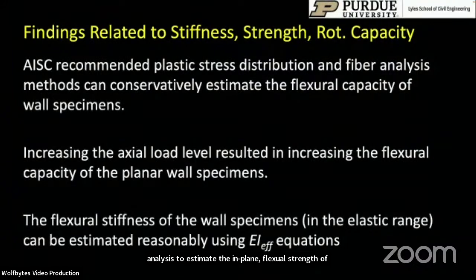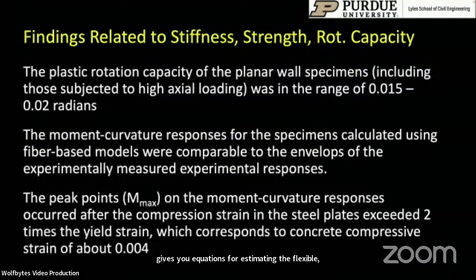It tells you that if you have axial load, you need to account for that, and it gives you equations for estimating the flexural stiffness of the wall specimens that is based on this research as well. In the commentary, it points out that the plastic rotation capacity of the planar wall specimens was in the range of about 1.5 to 2% in radians, and the moment curvature responses compare very well with the fiber-based models, and tells you some more recommendations on how to calculate the in-plane flexural strength.